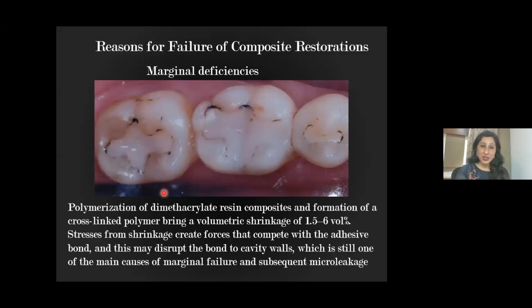The marginal deficiencies: the polymerization of composites and formation of a cross-linked polymer bring a volumetric shrinkage of 1.5 to 6 volume%. These are the stresses from shrinkage which create forces that compete with the adhesive bond. I told you that they compete with the adhesive bond. They try to fracture and fail this hybrid layer which you've made with your bonding agent. And this is why I talked about the bonding criteria in so much detail and so many times, so that it gets registered in your mind. Polymerization shrinkage is still one of the main causes of marginal failure and subsequent microleakage.